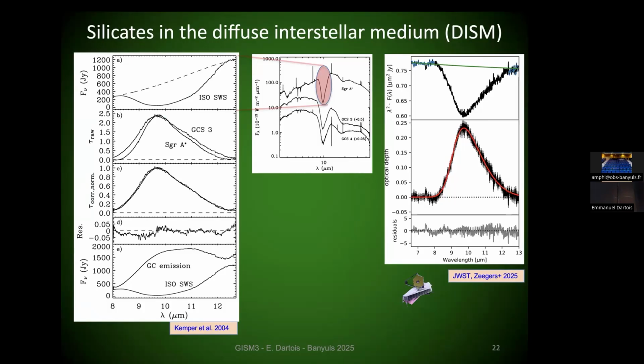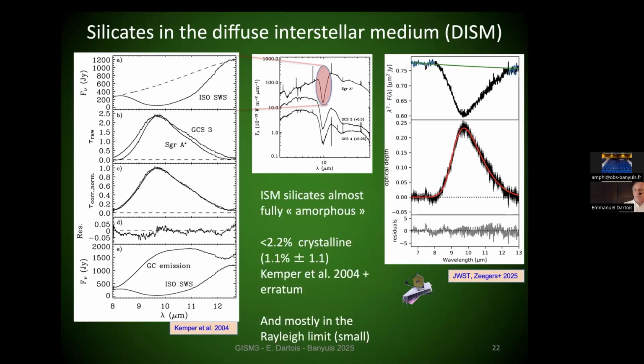And these are much more recent observations, looking again at the interstellar medium in our galaxy, but with the possibility with James Webb to look at lines of sight not necessarily toward the galactic center and with lower column densities, so trying to have a more representative view of the diffuse ISM. But the scheme is the same. You see basically a broad, asymmetric feature that is basically dominated by amorphous silicates. So the evaluation of the fraction of amorphous silicates is like 99% amorphous, and you have the residual here.